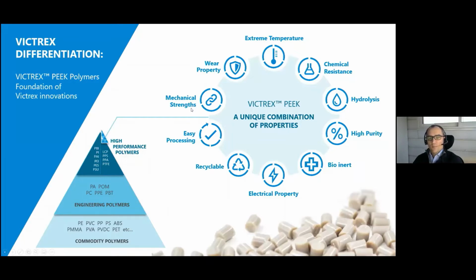So when it comes to mechanical strength, wear properties, temperature resistance, chemical resistance, for instance hydrolysis, high purity, bioinert or biocompatible, the electrical properties, it's recyclable, and it can also be processed. So PAEK really, if not the first one, ranks really high on those key engineering requirements. And as a rule of thumb, we used to say that if you need at least 3 of them, for instance you want to combine mechanical strength, temperature resistance, and chemical resistance, then PAEK can play a role.